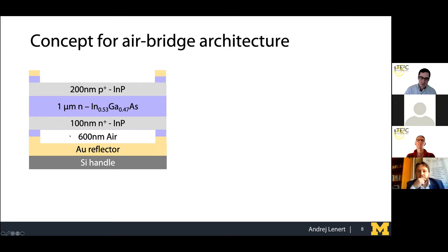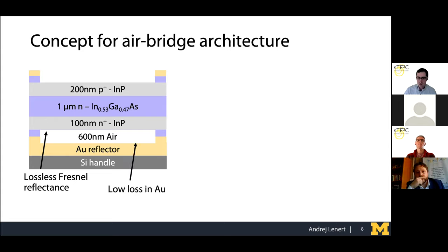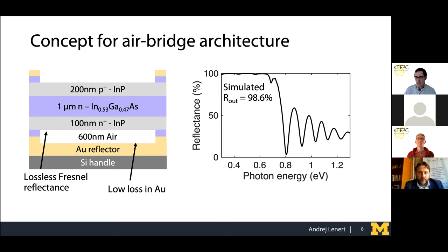And when I say nothing, I mean air. And so this was a pretty bold concept where, in theory, we could get to very high efficiencies because we have lossless Fresnel reflectance at each interface. We maximize the mismatch of refractive indices between the surrounding layers to the spacer. And overall, we could produce very high reflectances in theory. So this is another transfer matrix simulation showing we could get closer to 99% reflectance. And this is averaged over all incidence angles.